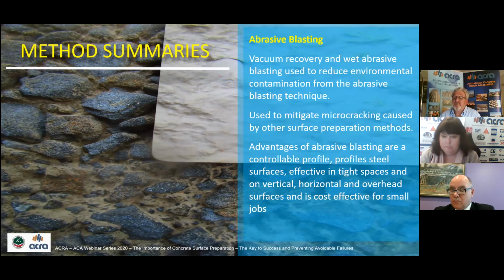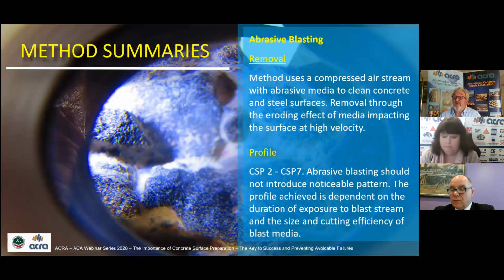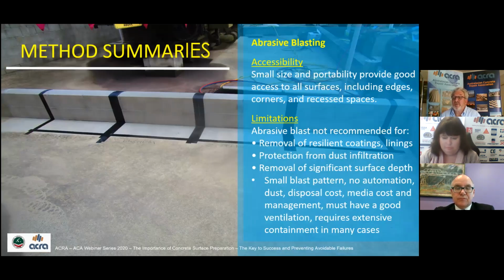The advantages of abrasive blasting are controllable profile, it profiles the steel surface, and it's effective in tight spaces. It's cost effective, even in small jobs. The removal uses a compressed air stream or water with an abrasive media to clean the concrete and steel surfaces. Removal is accomplished by the eroding effect of the blast media impacting the surface at high velocity. Surface profile 2 to 7. And once again, that will change depending on the duration of exposure of the blast stream on the concrete. Accessibility, small size and portability of hose and blast nozzle provide virtually unrestricted access to all surfaces, including edges, corners, and recessed areas.